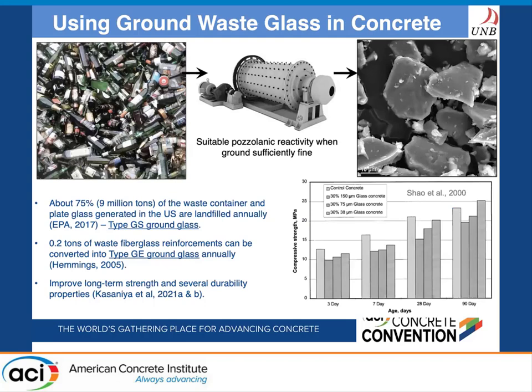A huge quantity of waste glass is produced every year, but only a small portion is recycled. The majority comes from plates and containers, which can be used to produce type GS ground glass. Another type comes from fiberglass reinforcements, which can be used to produce a low alkali or type GE ground glass. Waste glass can become a reactive material when ground to micron particle sizes. As ground glass is ground finer, its reactivity linearly increases — with a significant difference especially at 90 days when the pozzolanic reaction has progressed considerably.